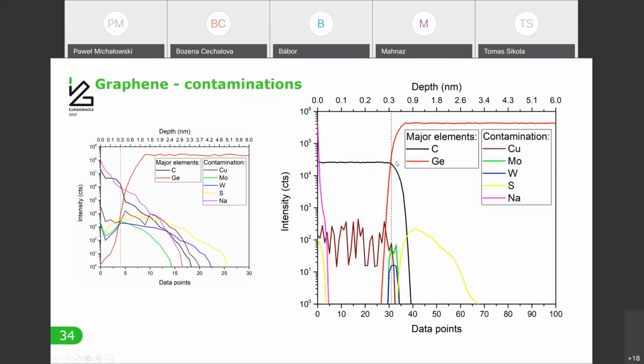There is a very clear difference between graphene, so the carbon signal decreases, germanium increases. And now we can see a very interesting thing, that on the very surface of this material, we can find sulfur and sodium, probably simply from air. The copper actually is introduced into the graphene layer, forming the copper graphene composite, whereas the molybdenum and tungsten are located at the interface between graphene and germanium substrate, and also some additional surfaces penetrating the germanium, which is not surprising since sulfur is passivating the germanium surface.